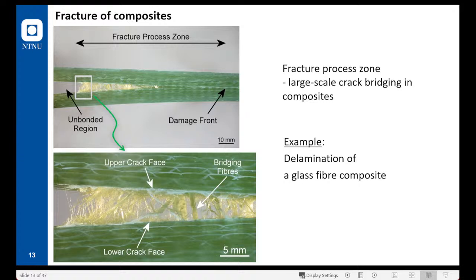Now let's see how composite materials fail. I will focus in this slide on unidirectional glass fiber composites. And this is an example where I have a DCB specimen, and I will apply forces in this direction and in this direction, so I will open the crack. This is the crack tip here, but you can see that behind the crack tip, there is a large area where fibers are connecting the crack faces. And this is what gives damage tolerance to composite structures. And also, as you can see here, this is the crack tip. All this is the damage zone, so it's a large-scale fracture process zone, typical for damage-tolerant materials.